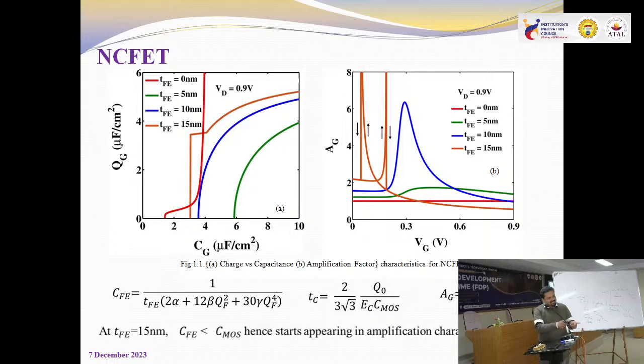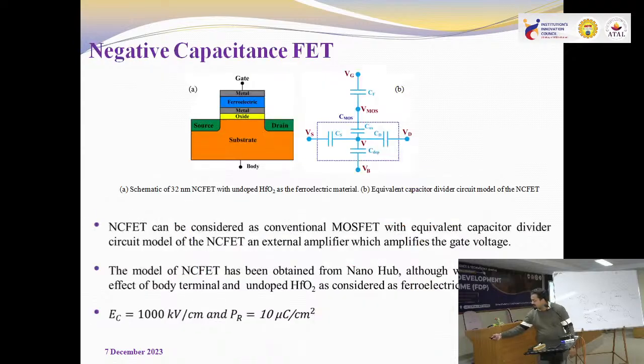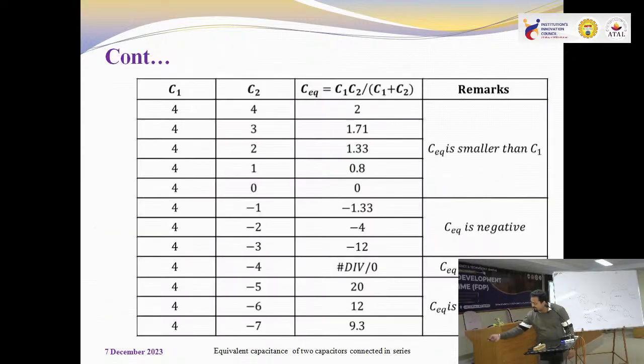So not necessarily, critical thickness will not be 10, because everything is dependent upon matching of two capacitances. Like here, for this I showed now. This C1 is fixed, 4. Now this C2 is variable. Now where the two capacitances are matching close to each other.